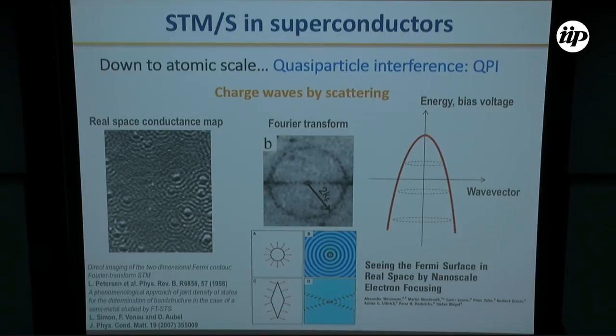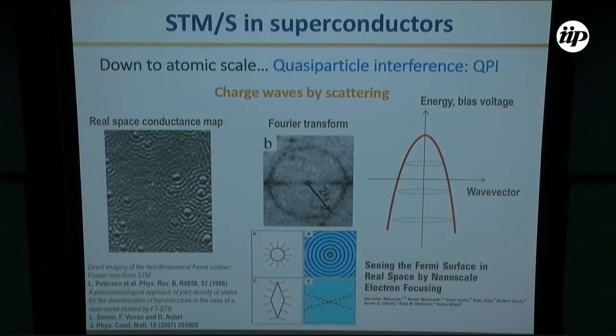Well, with the STM, we can get information not only in real space, but also in reciprocal space. We also saw some data yesterday using the quasi-particle interference imaging technique. Using this technique, essentially we obtain in conductance maps a standing wave produced by scattering of electrons at defects, and by studying the wave vectors and their dependence with energy, we can reproduce the electronic band dispersion. This is quite useful to study metals, but also superconductors, because we can directly see how the superconducting gap opens in the band structure. Also, we saw yesterday that this technique is particularly useful to study topological materials, and we saw some examples yesterday.